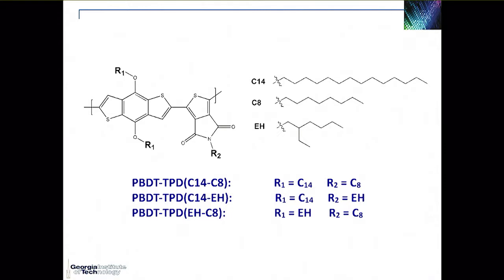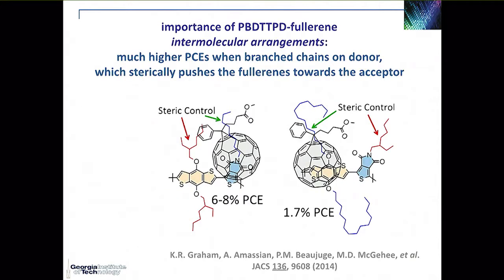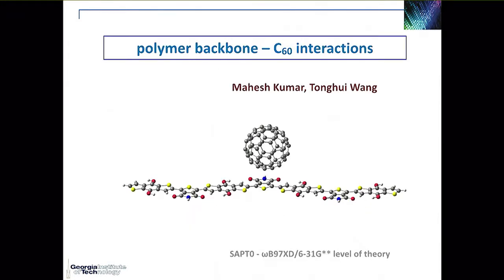And the impact is actually extremely important, because as you go from having branched side chains on the electron-rich part, which from a steric standpoint, very simply, would tell you that the fullerenes tend to go towards the electron-poor part, you get very significant efficiencies reaching 8%. In the other case, if you have a branched side chain on the electron-poor part, pushing the fullerene towards the electron-rich part, you get an efficiency that's lower than 2%. And so we wanted to understand what was going on there, what could be the reason for those differences.